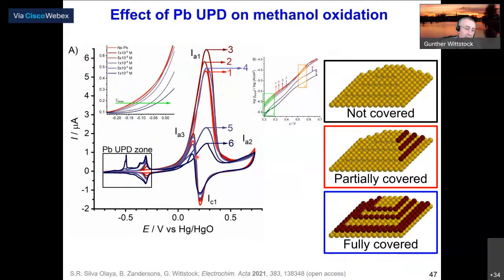Okay, so this can now be done in a similar way for different concentrations of lead, where we poison certain surface sites with lead and look for the effect on the methanol oxidation here. Again, we see the signals for the methanol oxidation and here the signals for the UPD. In the insets, you have a few regions of this voltammogram enlarged. This one belongs to this region, and here is the Tafel slope made over that area.